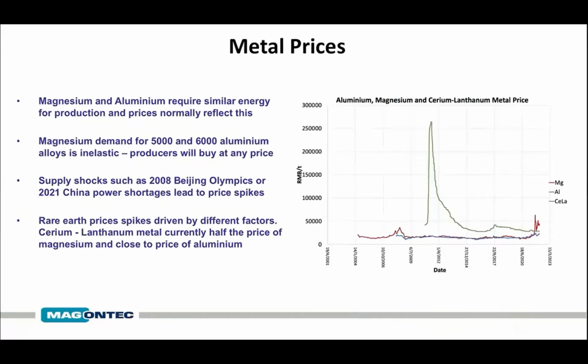Here I have some price history showing magnesium in red, aluminium in blue, and for comparison, the rare earth cerium lanthanum in green. So you see there's been a few spikes in the magnesium price. One was in around the 2008 Olympics, and right now there's another spike with the energy shortages in China. Because magnesium is essential for the 5,000 to 6,000 aluminium alloys, the demand there is inelastic. They will pay whatever price because there's no alternative to magnesium. So when there's a supply shortage, the price spikes up quite high. And interestingly, magnesium is more expensive than rare earth, and aluminium is getting close to the price of rare earth, which is an unusual situation.